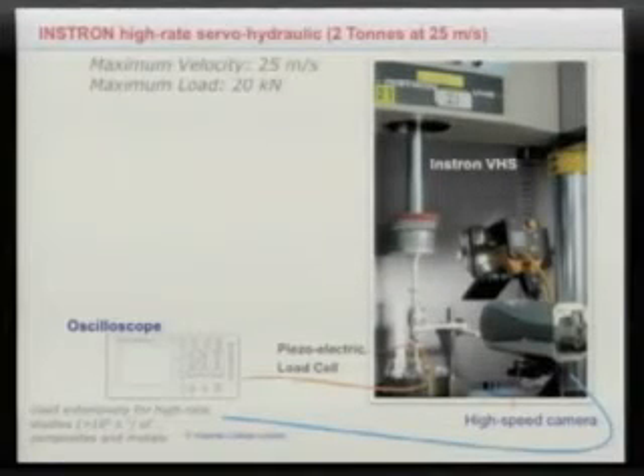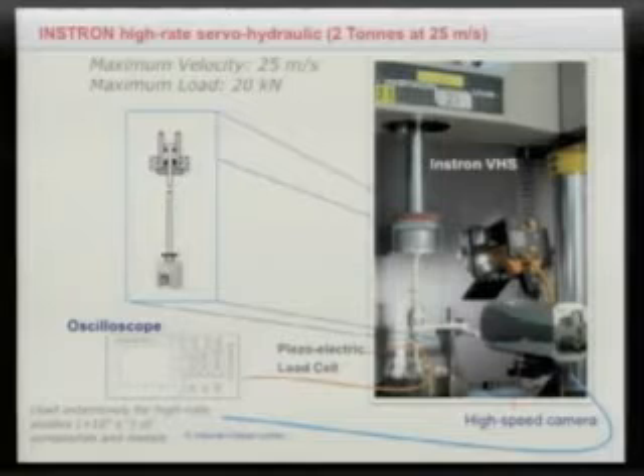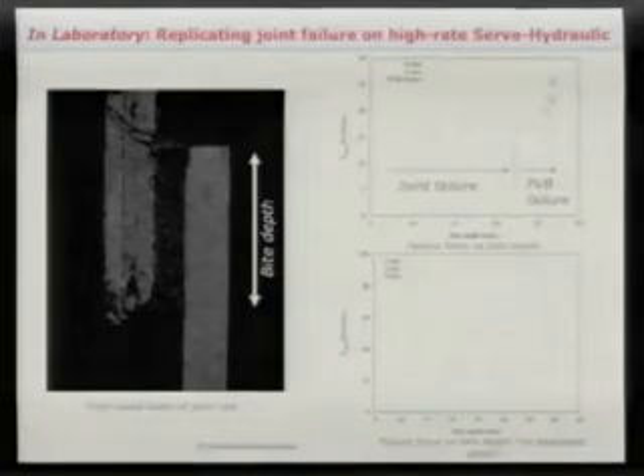What we then do is come back to the laboratory, just downstairs there, and we use our high-rate Instron, and this can load samples at speeds up to 25 meters per second. It has a very special design of what's called a lost motion device, where the shackle, which is loading the top section of the sample, moves initially, and then you get a sort of take-up condition which then loads the sample. That allows the grip to get up to speed before you load the sample. And we've got one of these tests just to illustrate this.